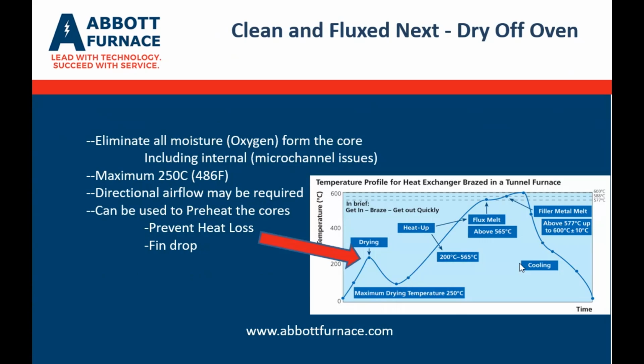Again, similar to the thermal degreaser, we're about 500 degrees Fahrenheit to dry the parts. And because of some of the complicated designs of the heat exchangers, directional airflow may be required instead of just heat alone. So in some cases, heat needs to be applied in certain areas to eliminate internal oxygen or internal water from the tubes.